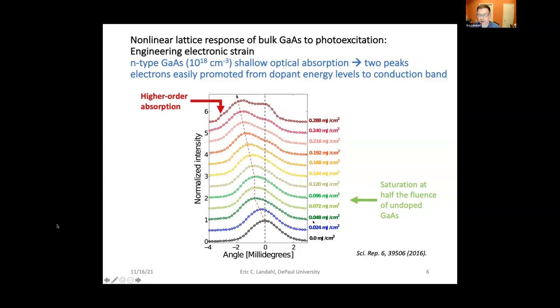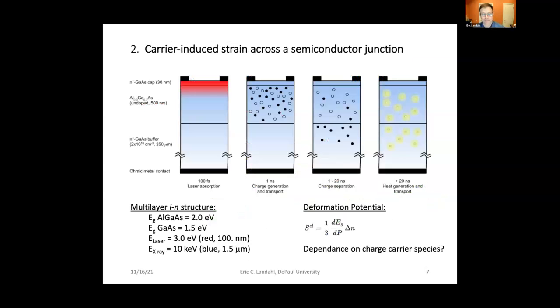So I think I've made the case that you can absolutely see, even with a slow probe, as long as recombination is slow and your spatial resolution is very high, it's only a couple of millidegrees across, implying femtometers of resolution, you can understand electronic processes by looking at high resolution diffraction patterns, even with lower time resolution. That's because essentially the electrons cause distortions which get frozen in place.